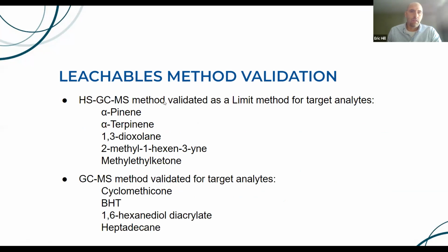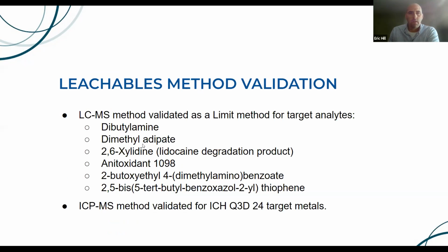The headspace method was validated for pinene, terpinene, dioxolane, methylhexene, and methyl ethyl ketone. GCMS was validated for cyclomethicone, BHT, hexanediol diacrylate, and heptadecane. LCMS method: dibutylamine, dimethyl adipate, 2,6-xylidine, antioxidant 1098, 2-butoxyethyl 4-(dimethylamino)benzoate, and a thiophene compound. And then the ICP-MS was validated for the ICH Q3D 24 target metals. And again, these compounds came specifically from our extractables data, which was then assessed by the toxicologist.